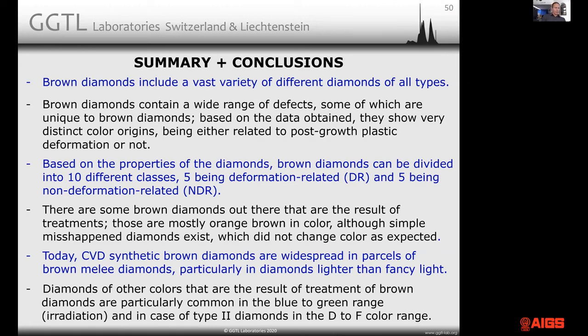On the color modification of brown diamonds by treatment, the most common thing you see in the market is melee, particularly melee in the blue to green range, where they use as a starting material, rarely colorless material, but usually brownish or yellowish stones. So brownish are cheaper, so why not use brownish? So that's just simply radiation. And in the case of type 2 diamonds, the D to F color range is the most common one where we observe stones that have been treated.